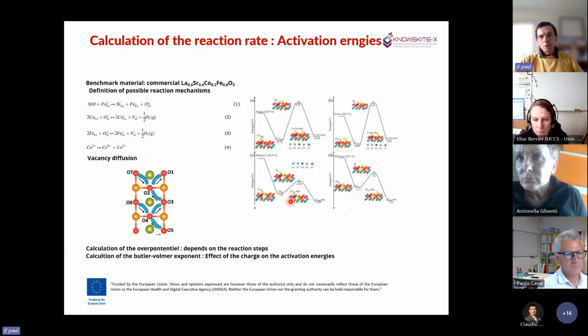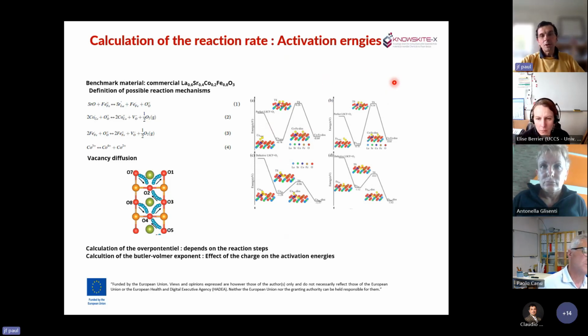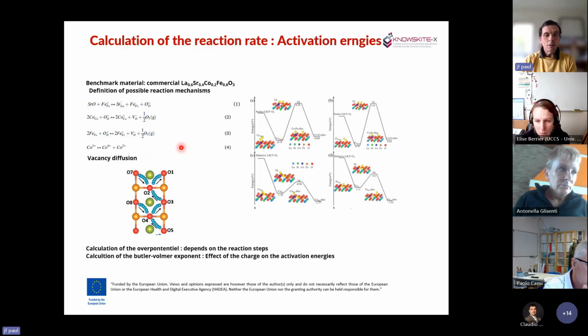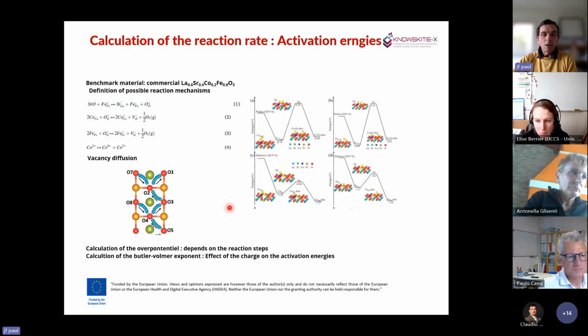It's possible, using the reaction mechanism, to compute the overpotential, and the overpotential will depend on all the steps that you have used or proposed in your reaction mechanism. And the overpotential will depend on the difference between the lowest intermediate and the highest intermediate. And this thermodynamic limitation will tell you if the overpotential for the reaction is high or low. And it's a way to also check if your solid is a good one or a bad one to activate either H2O or O2.